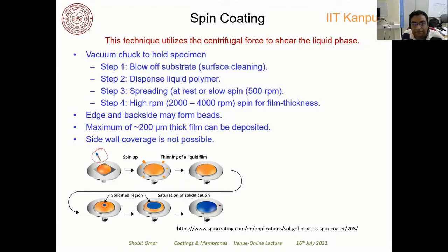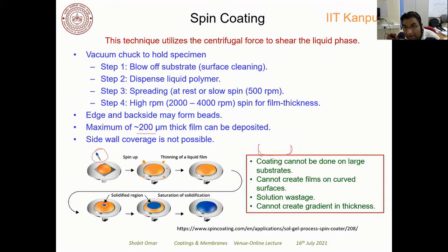Once it is done, if you dry it, the solidification will occur from the center, and then it slowly moves in a radial direction, and then finally you will get a solid film once you dry it. Okay, so this is how this process occurs, and the major issue with this is that you can only do it on a flat surface, and the maximum thickness that you will get is around 200 microns. Okay, so if you have surfaces where you have some type of side walls, you cannot use this technique. That's a drawback of spin coating.